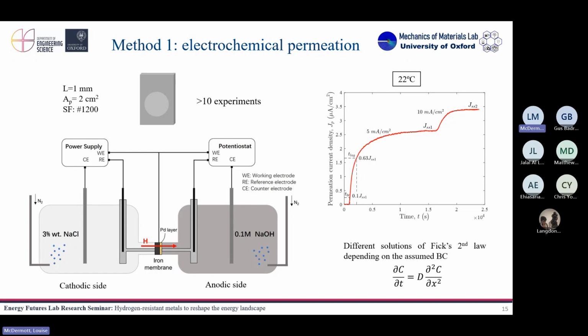Then you have a difference of concentration, a gradient of concentration. So hydrogen is going to try to diffuse to the other side, where I can detect it. What do I measure? I measure the time that it takes for hydrogen to get to the other side. So I start producing hydrogen, and once the first atoms get to the detection site, I start seeing a rise in this curve. That's basically an oxidation current that I measure here. Then, of course, at some point you reach a steady state, and you can produce more hydrogen on the left-hand side and produce a second curve. So you have those kinds of transients.